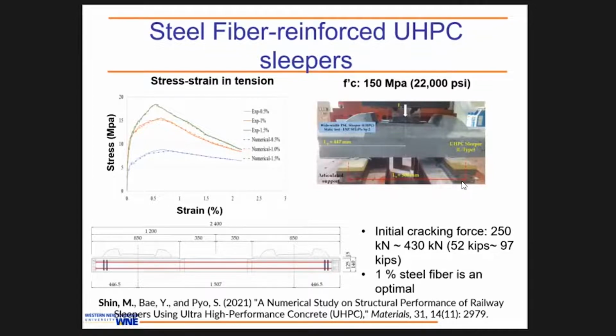So 15% reduction of what you're going to get from the direct tension test. And then we tested at the rail seat, and then we captured various mechanical properties. But what we have found is the initial cracking force is about 50 to 100 kips, which is significant. And also after that, it has really good post-peak behaviors. So this study shows that UHPC is great and also fiber is great, but the cost is an issue.